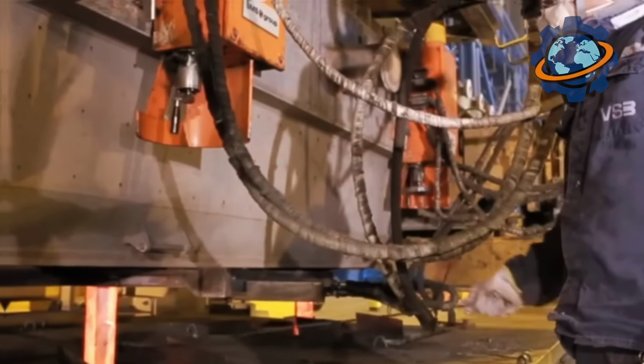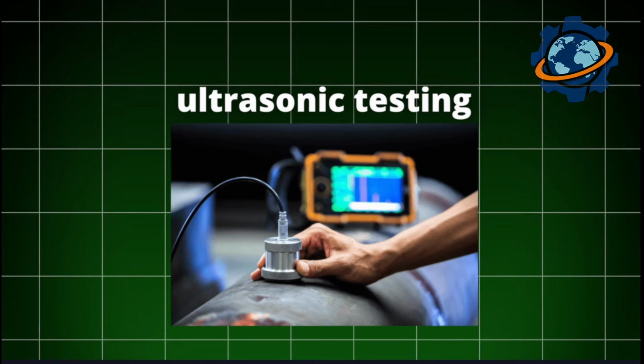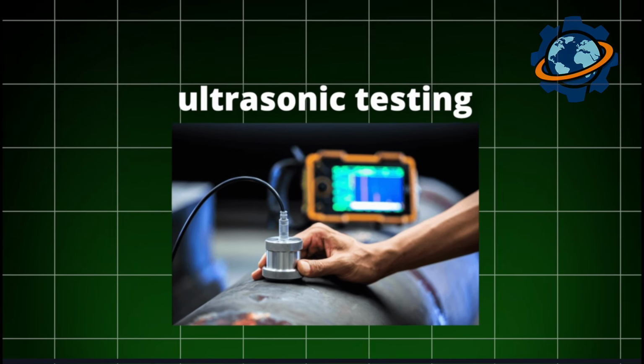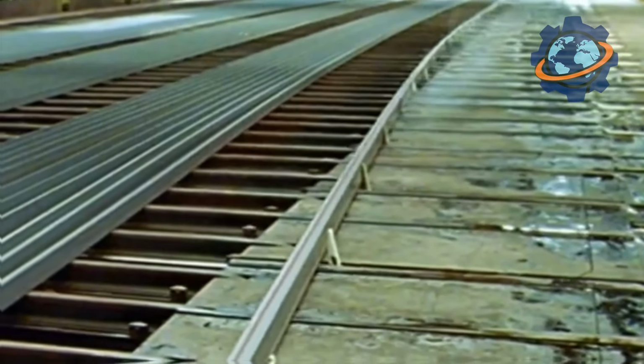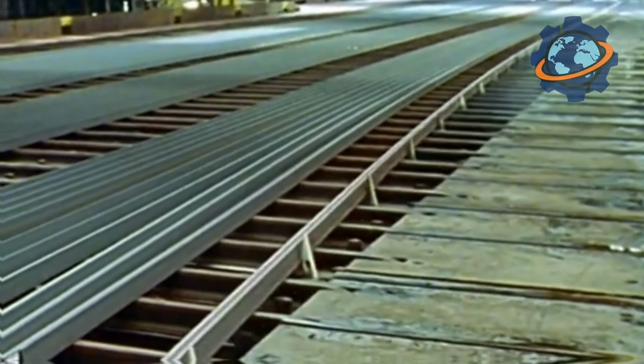In special labs, it's checked for strength, hardness, geometry, and internal defects. First up, ultrasonic testing. High-frequency waves are sent into the rail. If there's a microcrack or void inside, the signal bounces back and flags the problem. Then, hardness measurements along its entire length to make sure the heat treatment was uniform.